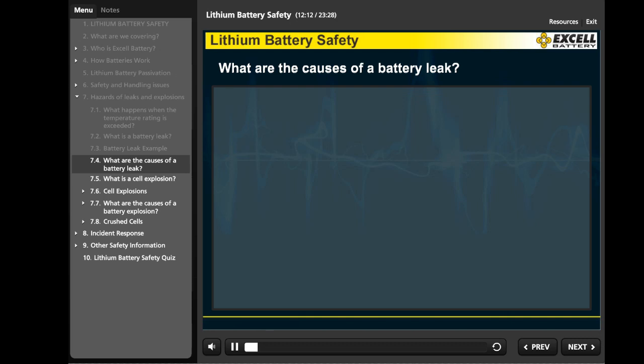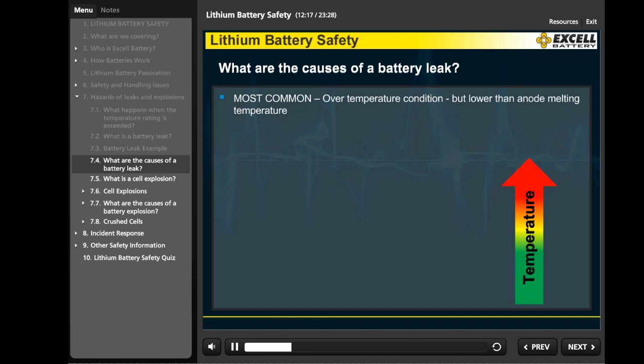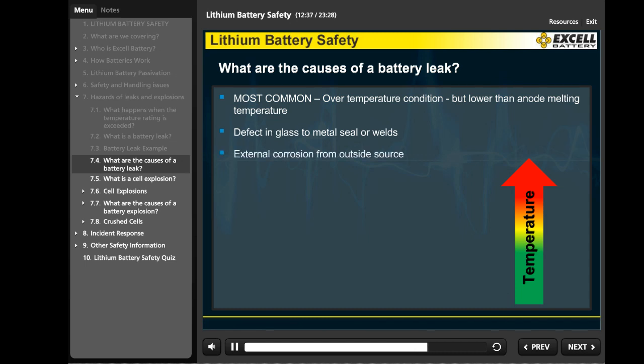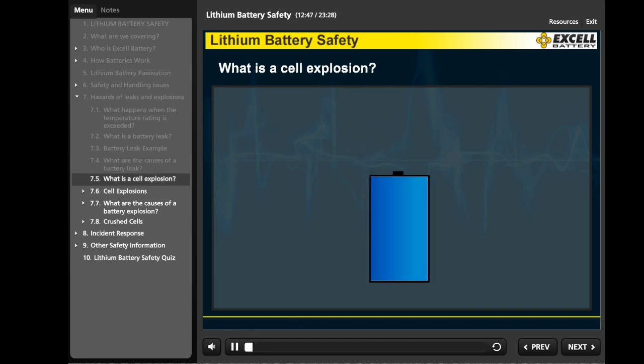What are the causes of a battery leak? The most common reason for a battery leak is an over-temperature condition, higher than the temperature rating of the cell, but lower than the anode melting temperature. As mentioned previously, the increased pressure from the electrolyte may cause the glass to metal seal to break, allowing electrolyte to leak out. Other less common causes of a leak are a defect in the glass to metal seal, which is very rare, or external corrosion from an outside source. In the latter case, external corrosion can eat through the stainless steel, thereby allowing electrolyte to leak out of the can.